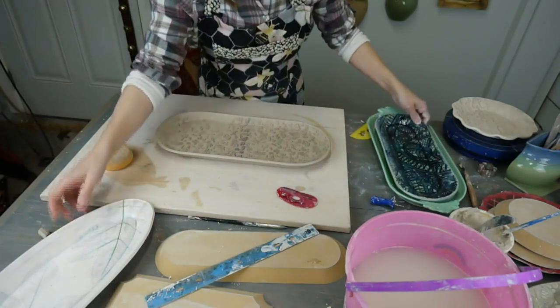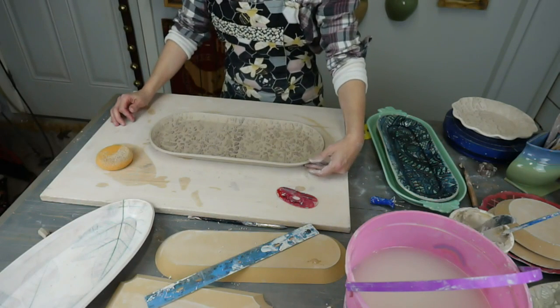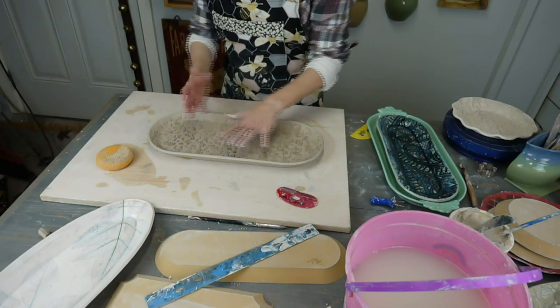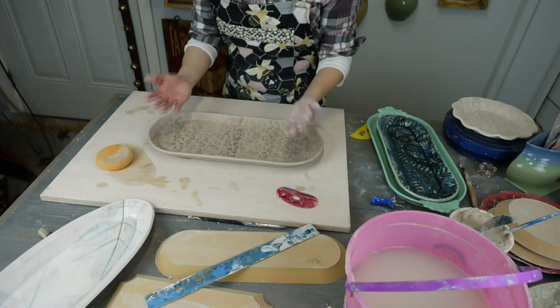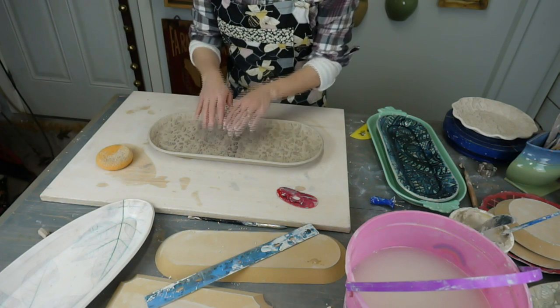After this is completely bone dry, the next step is drying physics. If you leave it just like this, the wood underneath is pulling moisture from the feet, and you have air above pulling as well. It's going to dry more on top, so what will happen is you'll get a bowing — these sides start to curl up, or the opposite happens and the middle pulls up.